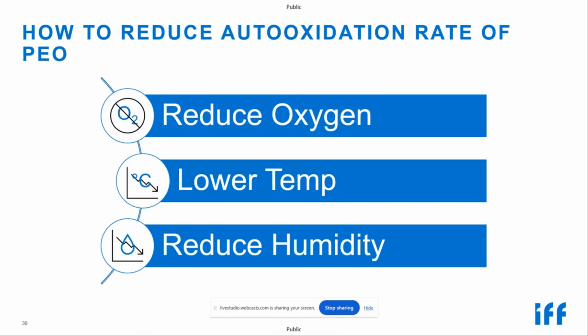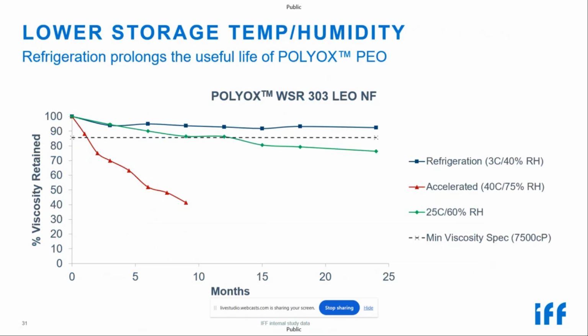How can we help reduce the autooxidation rate of PEO? I already showed that we add BHT to help reduce that rate. Storage conditions can help reduce the rate. So the first thing that I always recommend is to store as cool and dry as absolutely possible. This data is showing the viscosity loss of POLYOX WSR 303 over a 24 month time period. We stored commercial batches, this batch in a drum in refrigeration in the blue, another drum in a controlled environment of 25°C, 60% relative humidity, and then the third in accelerated conditions of 40°C, 75% relative humidity.